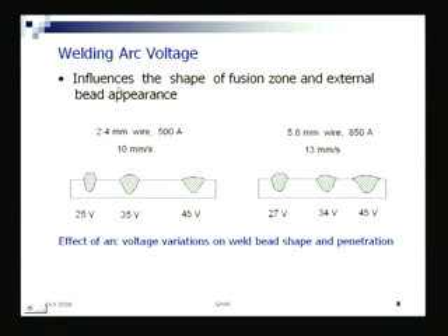Arc voltage influences the shape of fusion, primarily the external bead appearance. If the voltage is low, you have a narrow bead; if the voltage is high, you have a wider bead, for all other parameters remaining constant, say diameter, ampere, speed constant. So less voltage gives a narrow bead, higher voltage gives a wider bead, with depth of fusion more or less the same.